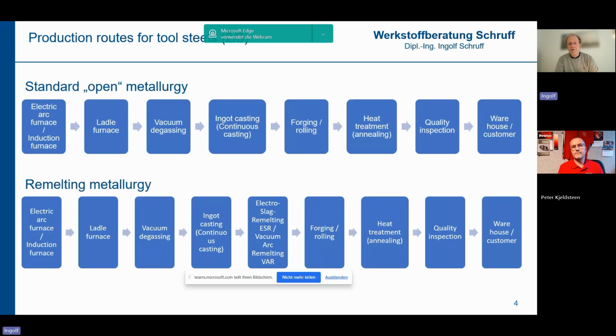This forming process is then followed by a heat treatment process, which certainly includes several processes to transfer the material into the defined annealed, soft annealed condition. That means we have to follow some restrictions regarding the annealed hardness in which the material is sold. Then we also have in some applications restrictions regarding the so-called soft annealed microstructure. All that is done in the heat treatment processes. And then follows quality inspection before the material is sent to the warehouse or customer.